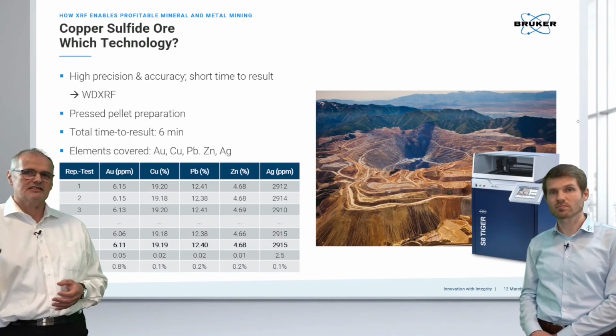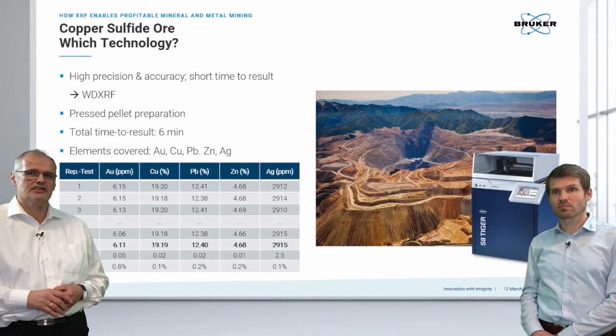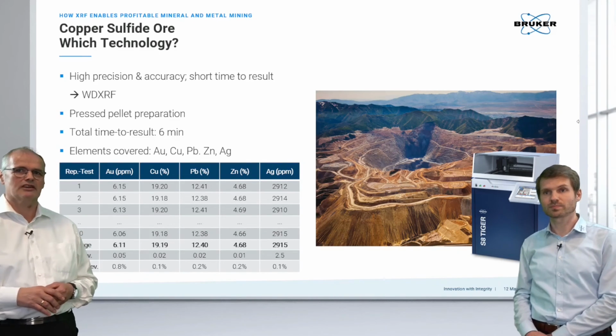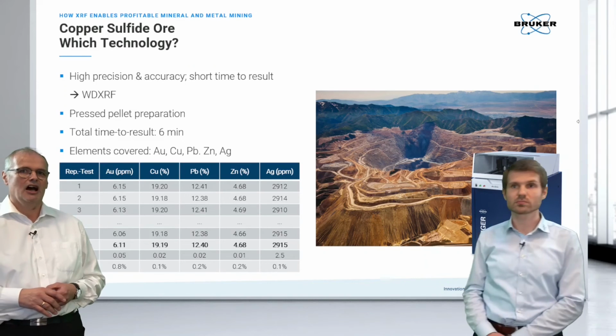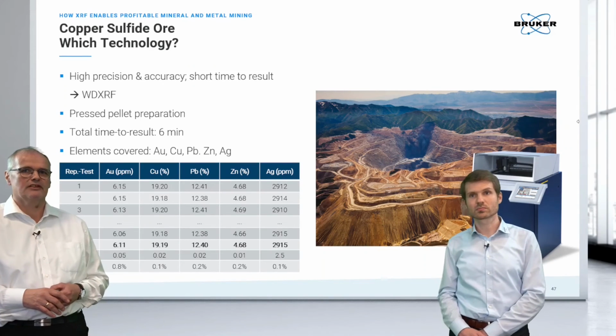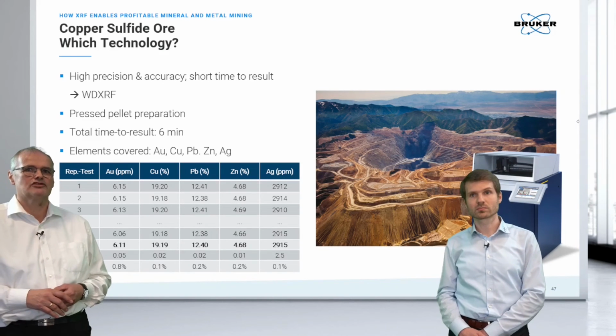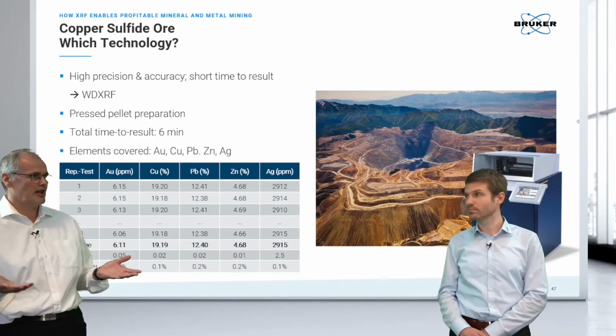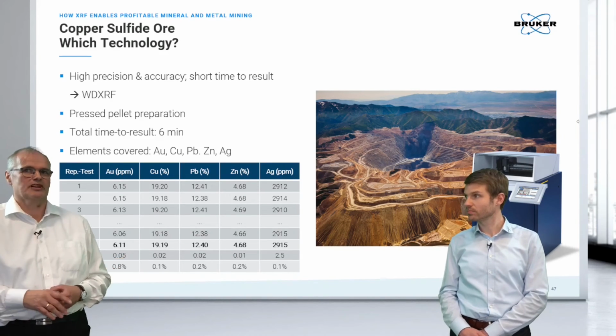And the nice thing is here you see the precision is again 0.1% relative for silver, below 1% for gold in the range of below 10 ppm. And yeah, copper is extraordinarily nice, 0.1%, the lead 0.2%. And that's a very nice concentrate, straight out of pressed powder, with a quick measurement time of 6 minutes.